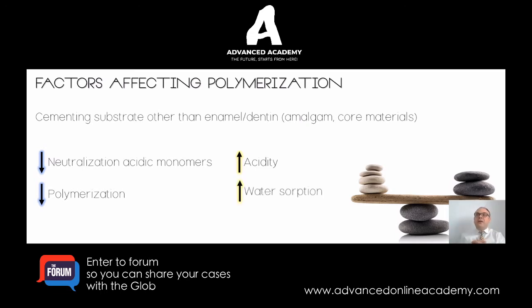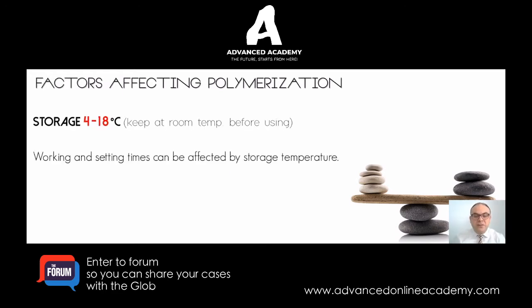So if you think about it, when you have an amalgam base, or another composite that's covering dentin completely, it's not going to be that wise to use a self-adhesive cement, because it relies on having natural dentin available so that this chemical process, or the polymerization process, happens optimally. So that's something to really consider when you have a core substrate of a different material other than dentin. It's not advised to use self-adhesive cements, because that will lead to degradation of the cement faster because of the water absorption process, and also it will delay the polymerization process as well.